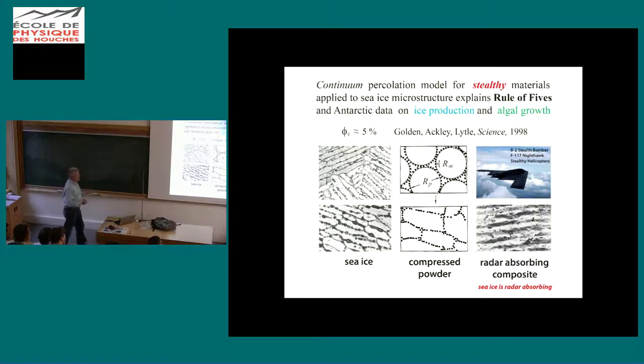All I did was take the continuum percolation model that was developed for these compressed powders and apply it to sea ice, and out pops the 5%. What's so interesting here is that these materials are so-called stealthy radar absorbing composites that they coat aircraft with to make them invisible to radar. And as a result, sea ice itself is a radar absorbing composite.